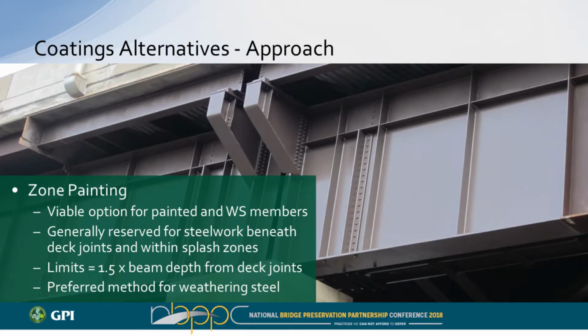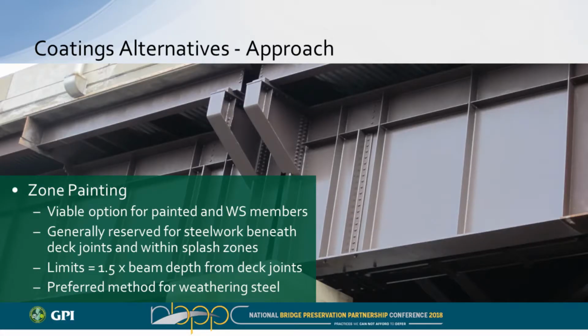And then zone painting. Zone painting really does apply to both weathering steel and painted steel structures. Here you're looking at primarily a zone or an area that you need to paint. Most often, with those deck joints, even with the painted steel bridges, it's typically the ends that are in the worst shape, right? So the weathering steel, same thing. If the deck joints are failing, or you're getting moisture and chlorides in there, it's going to fail that steel earlier. So we just need to address that particular area.